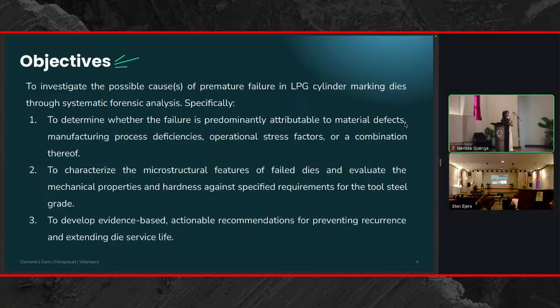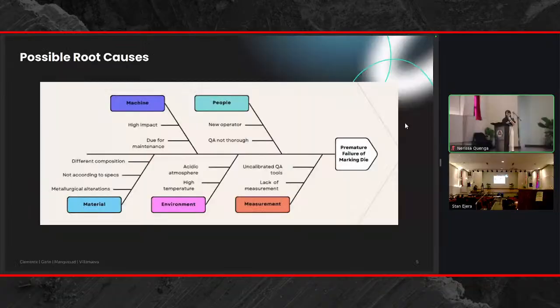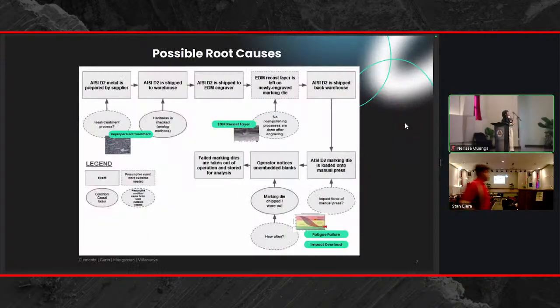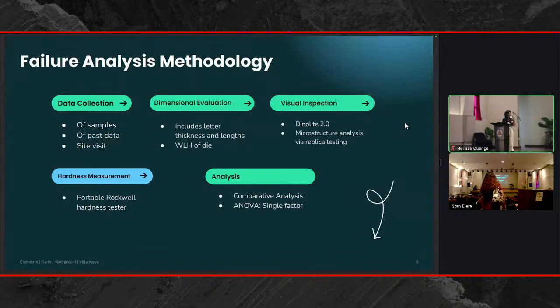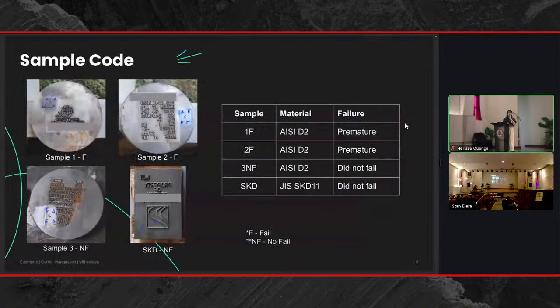Because of that, these were the theoretical causes of degradation and failure that we proposed. The first is the EDM recast layer, improper heat treatment, fatigue failure, and impact overload. Here we can see those integrated in our causal chart, showcasing the life of the AISI D2 as it's prepared by the supplier, heat treated, engraved, eventually used in the mechanical press operations, and where it eventually failed. Our failure analysis methodology largely constitutes visual inspection, hardness measurement, and later on metallographic analysis.